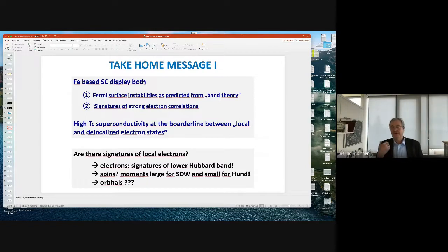And that's not only the case in iron-based superconductors. It's also what people discuss in the cuprates. If you go to all these cerium-based superconductors, which are more strongly correlated, superconductivity also occurs when you weaken the correlations. So it's quite characteristic. Unconventional superconductivity occurs just at the borderline. This is also the case, at least in my understanding, for these iron-based superconductors, where the correlations are, however, weaker than in the other unconventional superconductors.